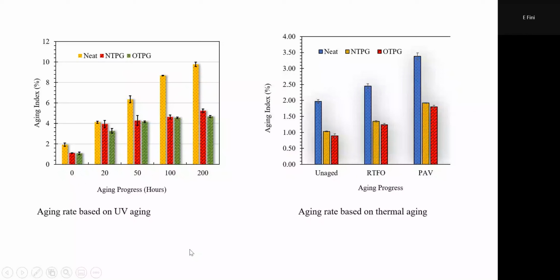So after you even meet all those specification criteria, you have to worry about how my material will age over time. Some materials may be very good at the beginning, but as soon as you expose them to 1 or 2 cycles of aging, they will just degrade really badly. So we have to look at the aging, and I caution you again when we talk about rejuvenation later on, when you improve a property at the unaged status, you're not done. You have to look at the aging trajectory of this material, because it could be really bad after several years, and you don't change the asphalt every year. You're designing for many years. So aging